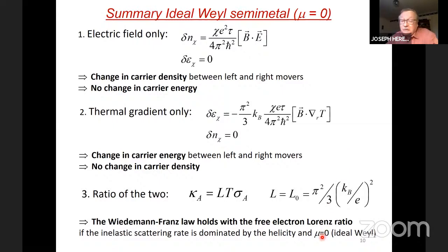By the way, this only holds if the chemical potential is at zero. So in other systems than the one I will talk about, where you have trivial pockets and you have the chemical potential somewhere in one of the Weyl bands, this does not hold. This strictly holds for an ideal Weyl semimetal.